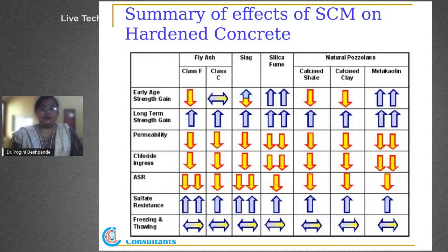All the cementitious materials always benefit long-term strength gain, and typically compared to controlled concretes for the same water to cement ratio, anywhere between 5 to 7%, up to about 30-35% increase of strength can be achieved.